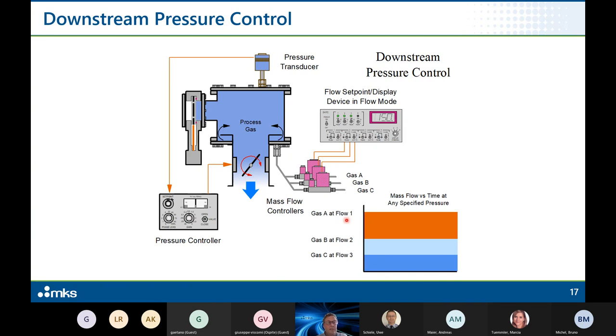And you see now we could adjust the pressure without changing the total flow of the gas mixtures injected to the chamber. So we have one more parameter to optimize our critical process, and that's very often required.